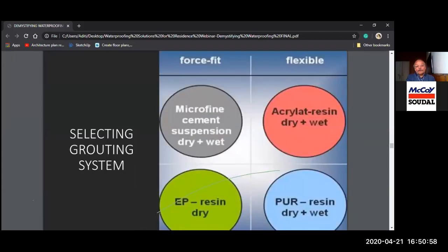So this is how you select your grouting systems. Microfine cement suspension for dry and wet areas, flexible areas like acrylate resins for dry and wet areas, epoxy resin for dry areas, polyurethane resin for dry and wet areas both. So as I said earlier, the selection of the product and technology is the most important thing. While doing your analysis and inspection, after that, this is one of the major things: the right selection of the product and right application.